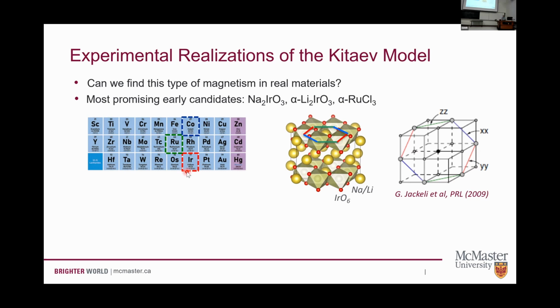The idea is that in these honeycomb lattice materials, we've got iridium-O6 octahedra. They're edge sharing, so that gives us the right bond geometry that we're looking for. And you can imagine this maps onto a picture that looks like this. You've got a honeycomb up at the top here. Because these iridium-O6 octahedra are tilted slightly, you get different orbitals overlapping along each of these bonds that we've shown in blue, red, and green. This is what gives you the potential for these 3 different interactions from the different orbital overlap.